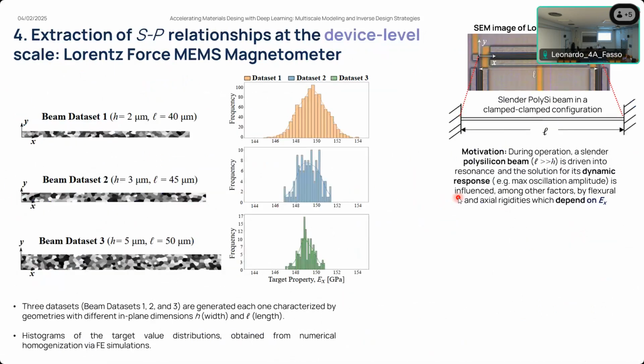Next, we scale up the analysis and then we perform extraction of structure to property relationships to the device level. Here we focus on a Lorentz force magnetometer, specifically on the resonance structure of this MEMS device. The motivation is that during the operation of this kind of device, a slender polysilicon beam, which is characterized by a much longer length than the width of the beam, is driven into resonance, and the solution associated to the dynamic response of this device, which is characterized, for example, in terms of the maximum oscillation amplitude, is influenced, among other factors, by the flexural and axial rigidities, which depend ultimately on the effective Young modulus along the axial direction in this structure.